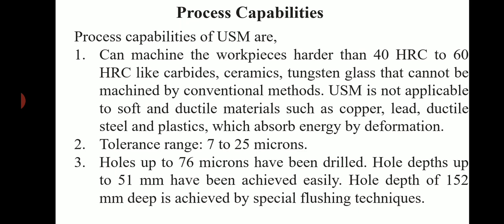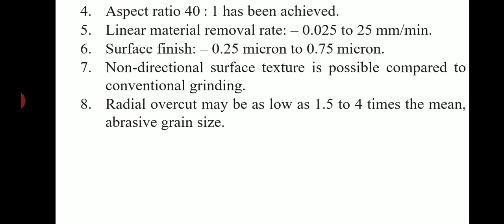Holes up to 76 microns have been drilled. Hole depths up to 51 mm have been achieved easily. Hole depth of 152 mm is achieved by special flushing techniques. Aspect ratio 40:1 has been achieved. Linear material removal rate is 0.025 to 25 mm per minute.